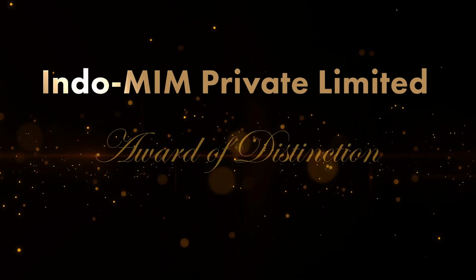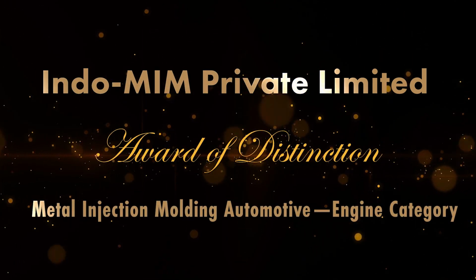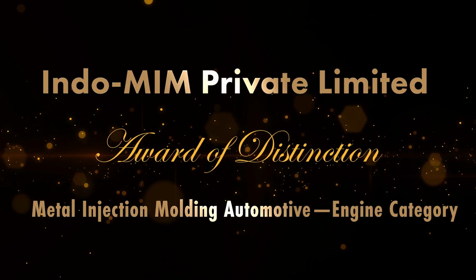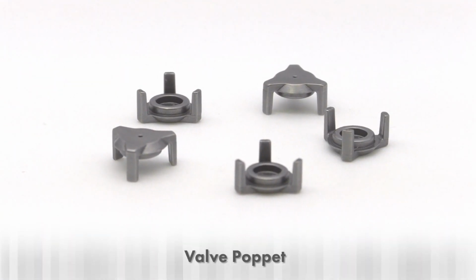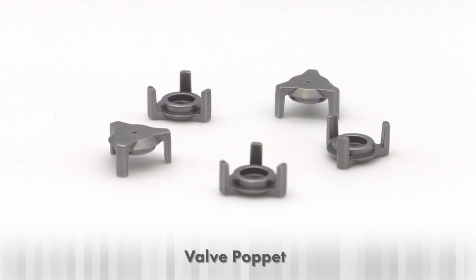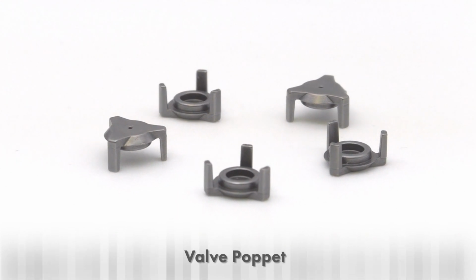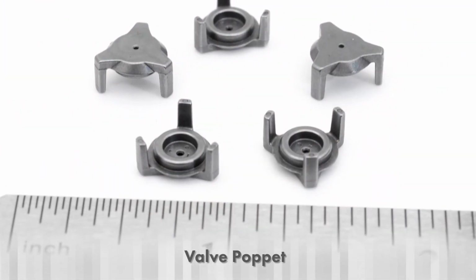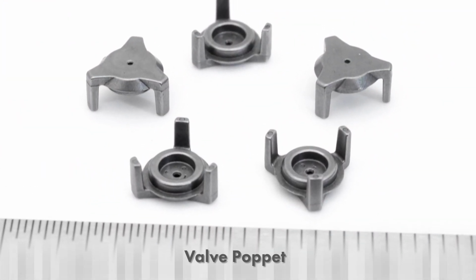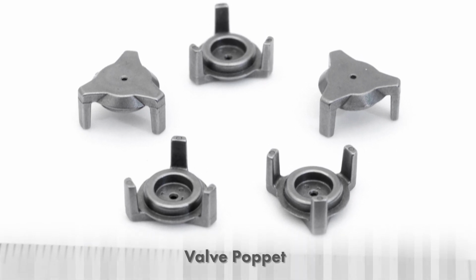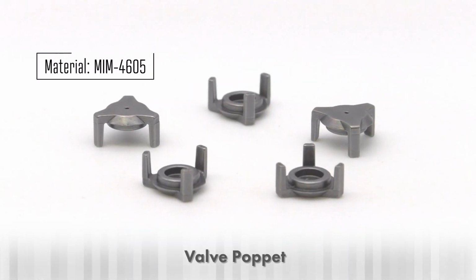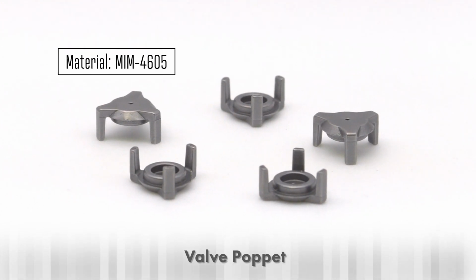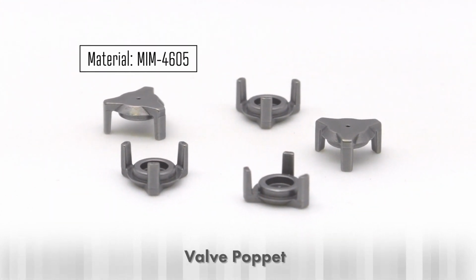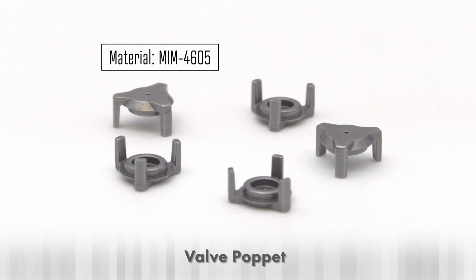Indo-MIM Private Limited has won an award of distinction in the Automotive Engine category for MIM components. This award-winning component is for a valve poppet used in the fuel injection system of a diesel engine for heavy trucks. The extremely small part has a tight tolerance on its outside diameter and the perpendicularity of the three legs. Part-specific forms were used during sintering to maintain part quality. Made from MIM 4605, quenched and tempered, the part is subjected to a barreling process to improve surface finish.